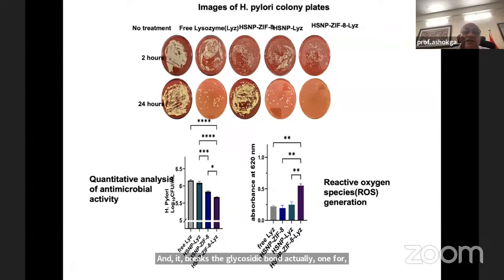And so we use lysozyme and the ZIF8 silica nanoparticle together, which also releases reactive oxygen species. So you can see that when you have both the silica nanoparticle with the MOF, here the MOF is ZIF8. In the previous example, the MOF was ZIF90. There are two different metal organic structures. This is like, you know, material chemistry. And there is a reason to choose this particular MOF along with the silica nanoparticle.